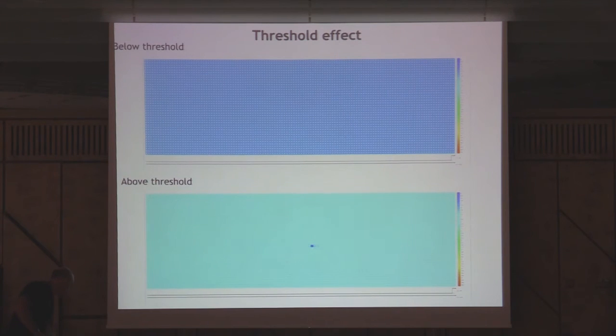You can do this beneath the threshold. If you do that, you see that some points go metallic, but before any segment can be formed, this kills itself. In this case, it's like walking in Paris on a typical day where it drizzles, but it doesn't really rain. So people do not use an umbrella anymore. You just go out, and you don't get soaked, because your body heats up and you dry at the same time. You get wet by the drizzle, but you never get drenched.